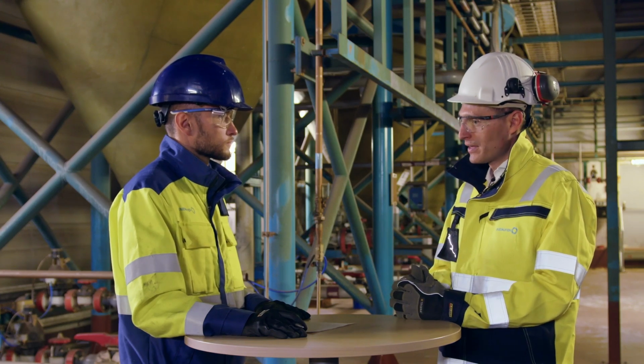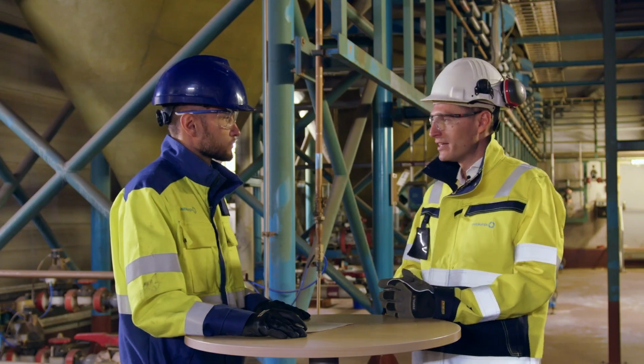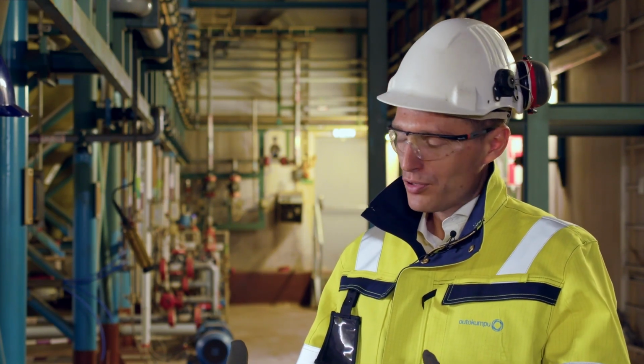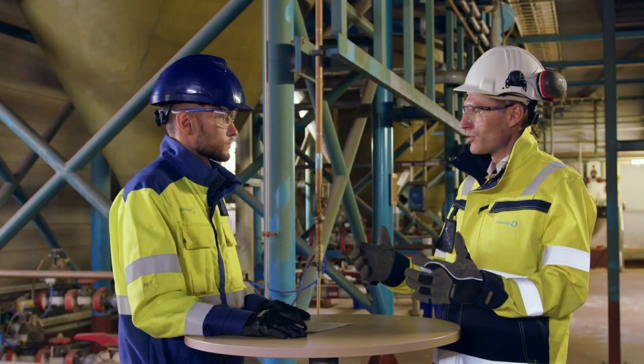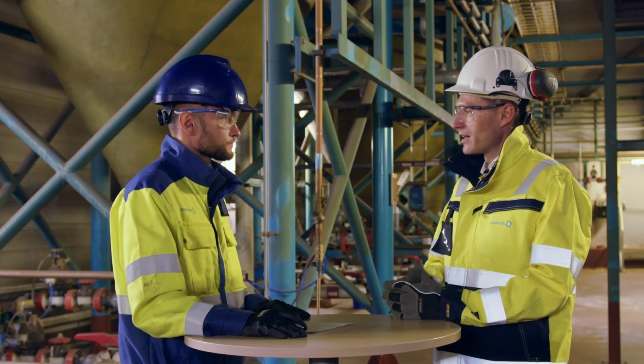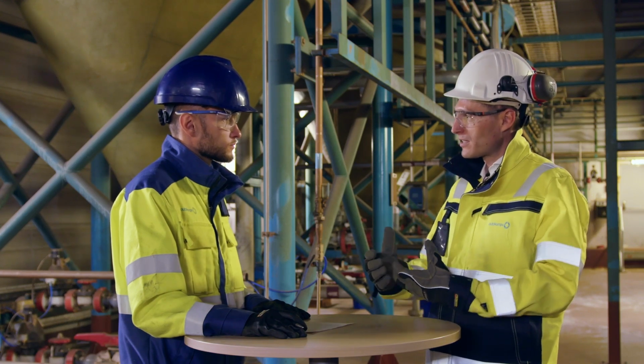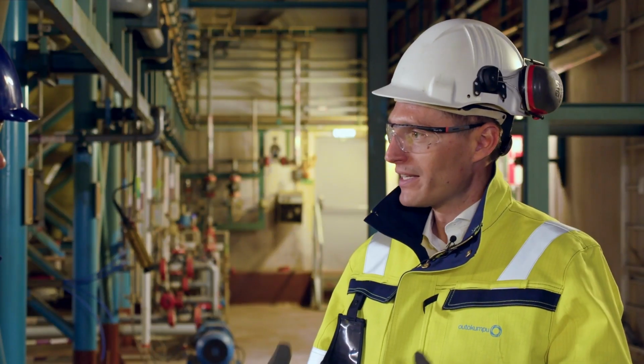And then we also have risks due to our production environment. Let's take, for example, the acid treatment area where we actually are. We have to pickle our material, and why do we have to pickle this? When we produce stainless steel, we first have the melt shop. You produce a slab, you go through the hot rolling area, and then come to the cold end. You have to reduce the thickness in several steps, and you have to recrystallize the material. When you recrystallize, you have to bring in energy in the form of heat. Due to that heat, you also build up scale.